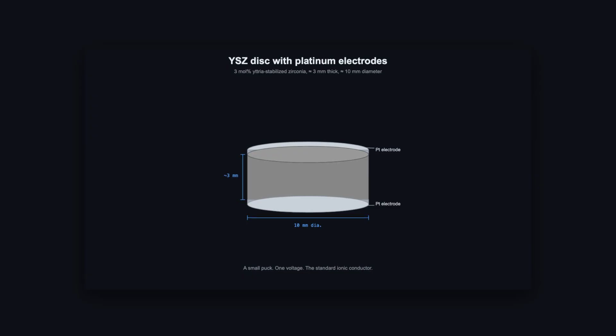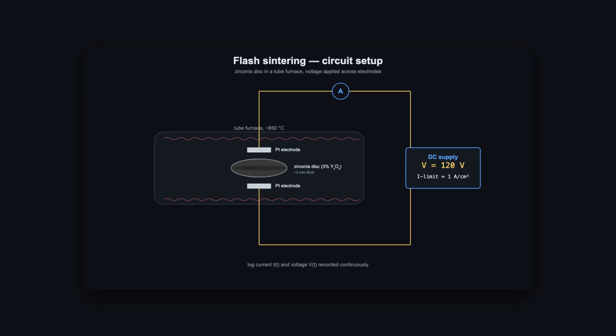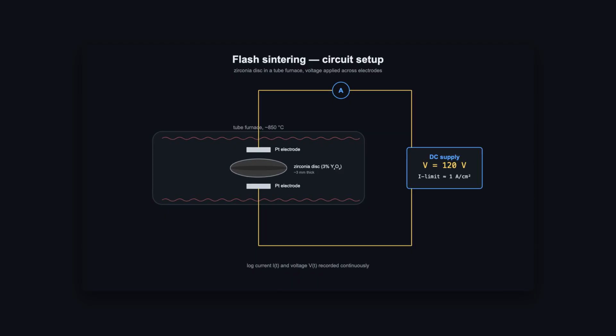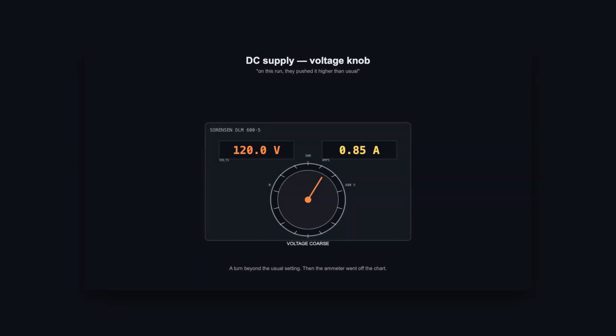Yttria-stabilized zirconia, 3% yttria, the standard ionic conductor. A disc roughly 3 millimeters thick, platinum electrodes top and bottom, sitting in a tube furnace. Hold the furnace at 850 Celsius, way too cold to sinter zirconia conventionally. At that temperature, in a normal experiment, nothing happens for hours. They had been varying the voltage in small steps, looking for incremental effects. On this particular run, they pushed the voltage higher than usual.